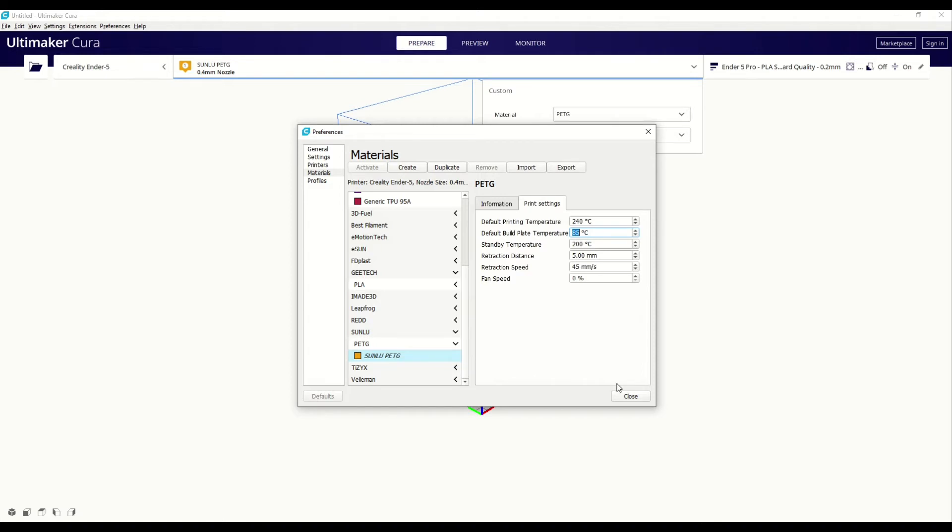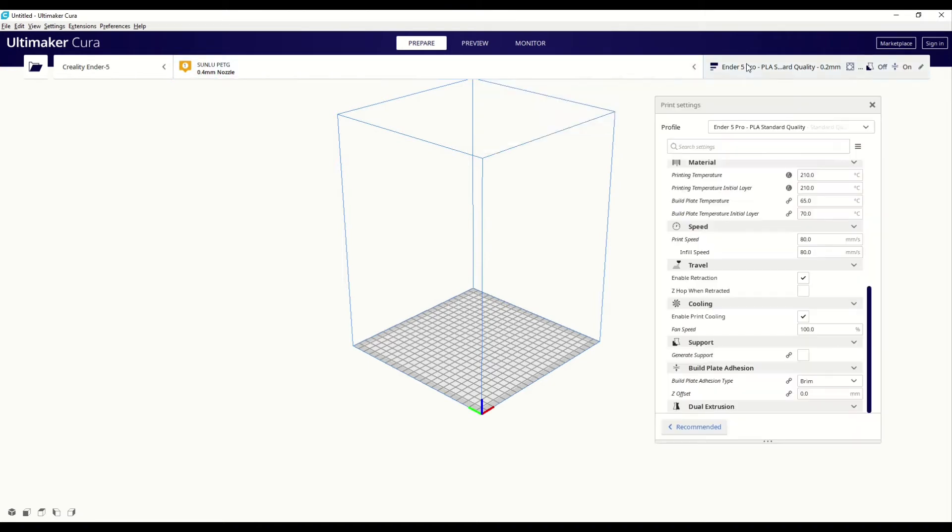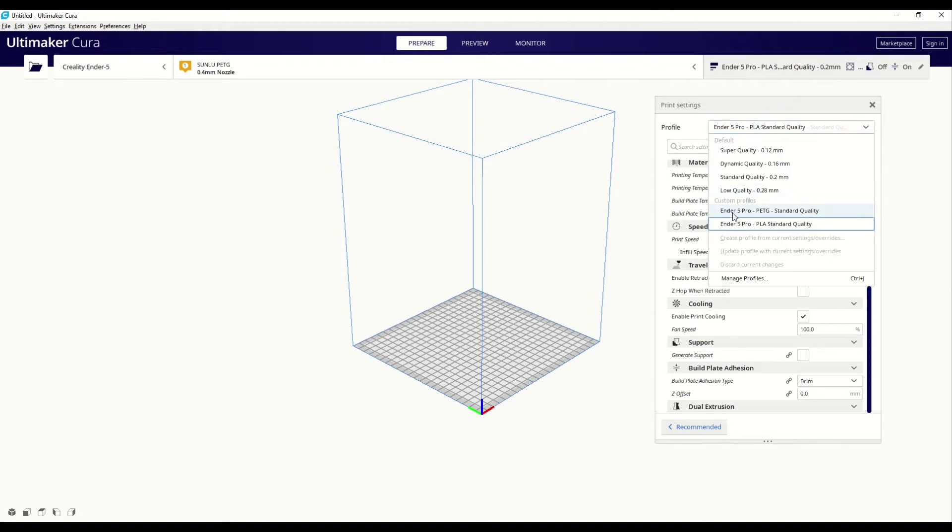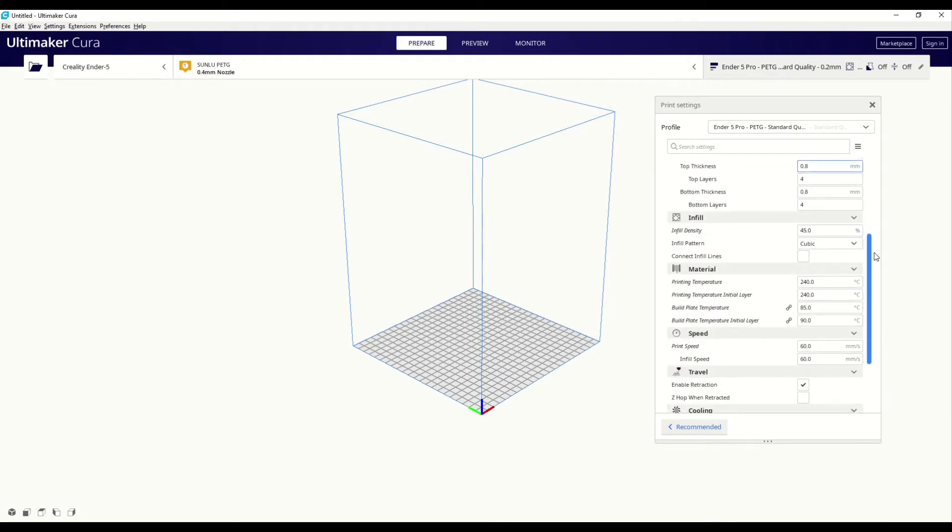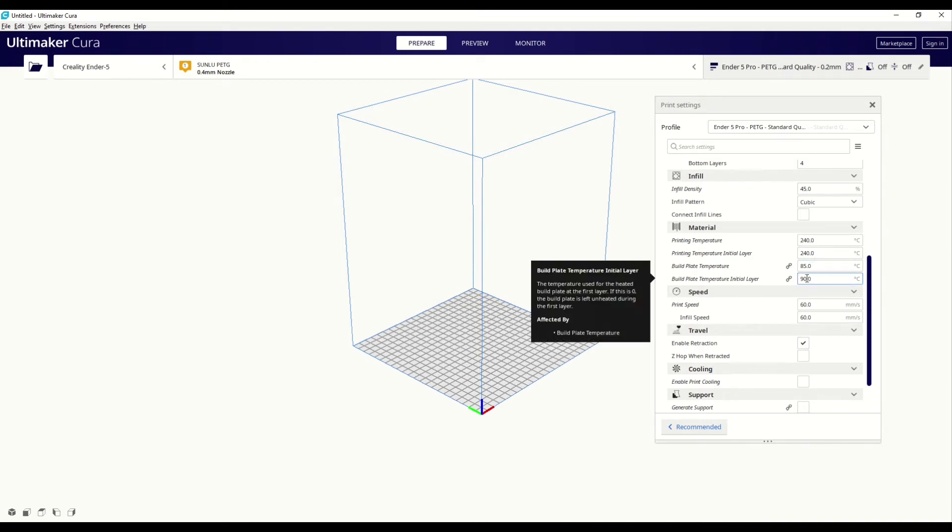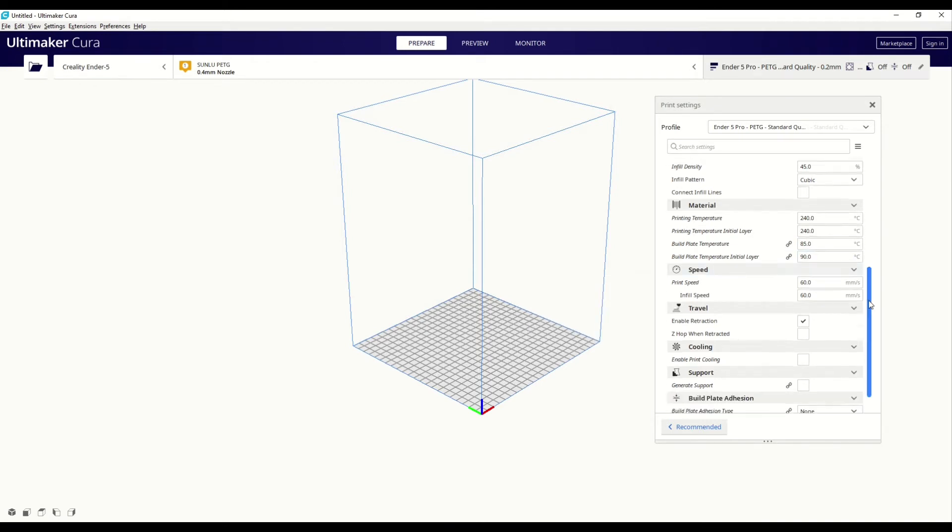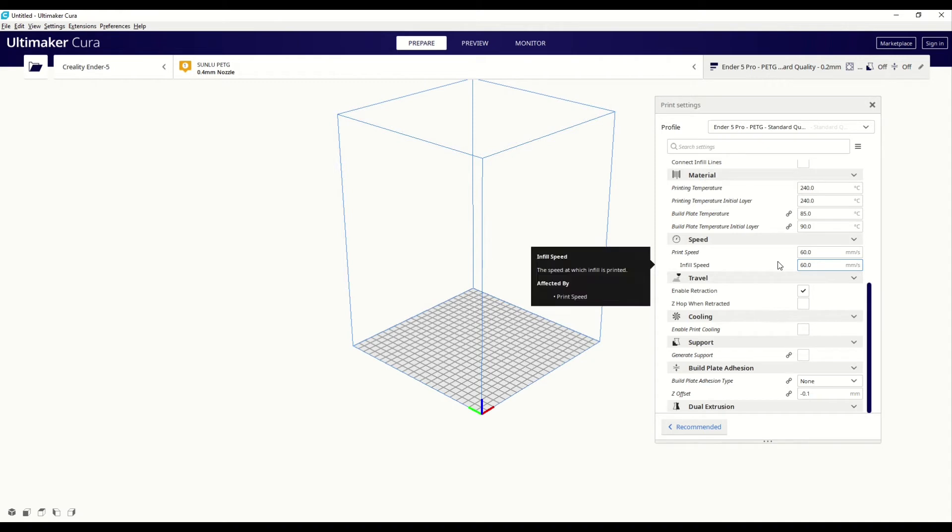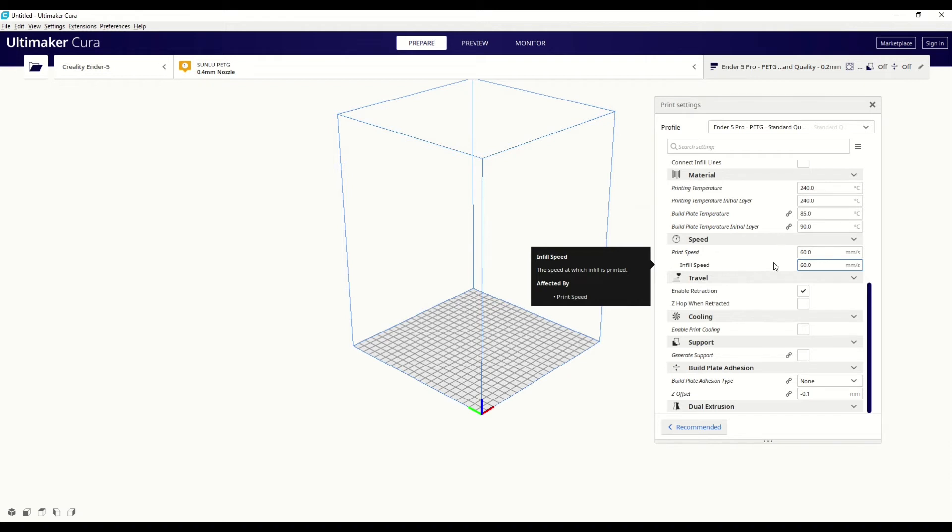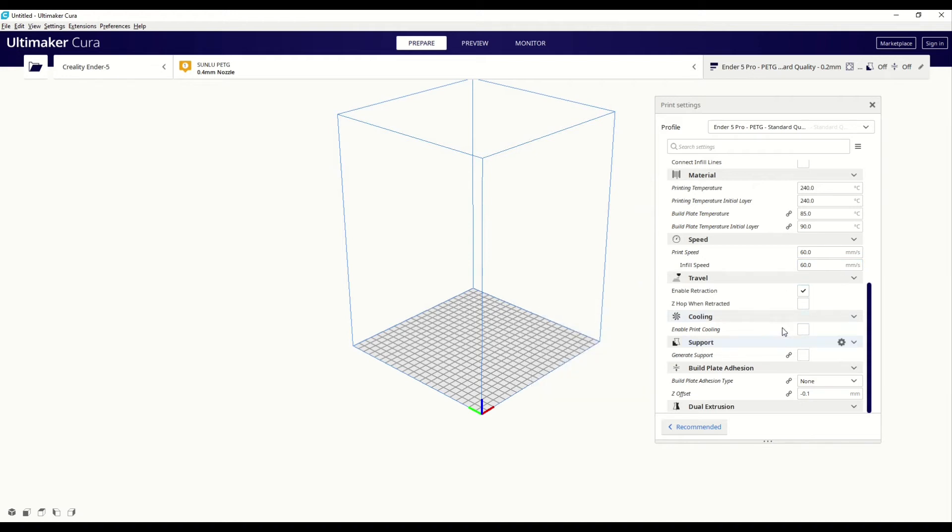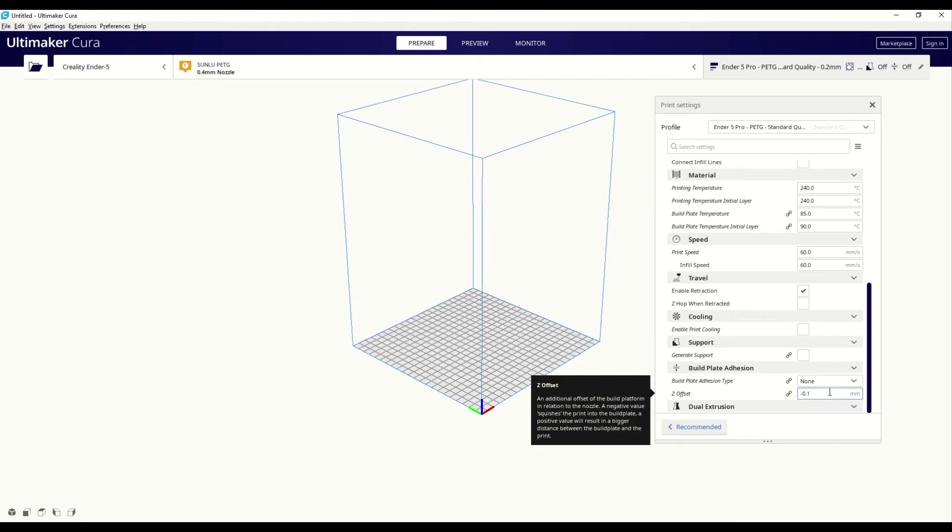As well as creating the custom material, I also created a profile with some additional changes. So if we look here I've created one for the PETG and as I mentioned before we have the 240 temperature, we have the build plate at initially 90 and then drop it down to 85. And I've also lowered the print speed down to about 60 because if it was any higher then I found that you start getting problems with the extruder starting to skip. As well as that I also noticed that if you did the infill too quickly then you had similar problems so I had to drop that down as well. And other than that, as you can see print cooling is turned off and yeah, the z-offset which I typically have a minus 0.1 just to help give that initial layer a bit more squish.